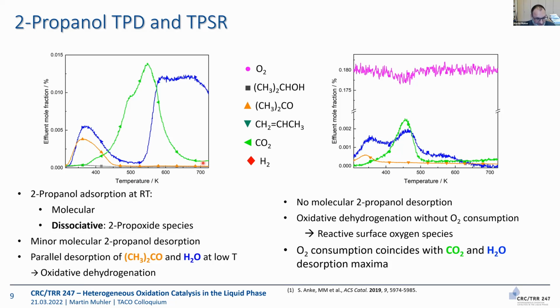Whenever you detect oxidative dehydrogenation, then you have to ask the question, is the oxygen of the catalyst involved? So is it gas phase oxygen that ends up in water, or is it oxygen originating from the catalyst, the Co3O4, that is actually a bit reduced and produces water in that way? And this can easily now be probed by temperature-programmed experiments.